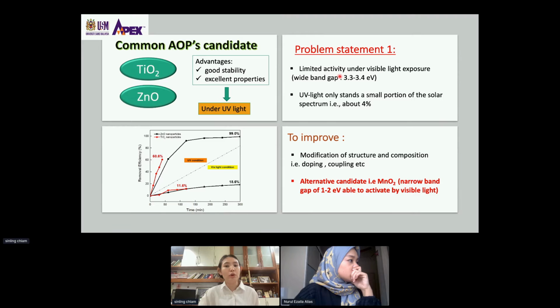In fact, as we all know, UV light only makes up a small portion of the solar spectrum, which is around 4%. As you can see from the graph here, under visible light conditions, zinc oxide nanoparticles and titanium oxide nanoparticles are only able to degrade less than 20% of the dye. So to improve their visible light absorption, modifications on the structure and composition of titanium oxide and zinc oxide have been carried out throughout these years using doping, coupling, and so on.